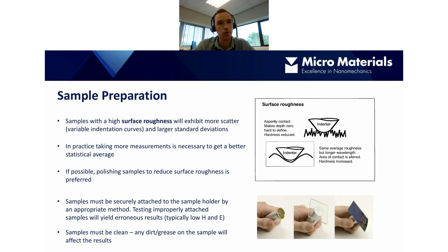It's also worth mentioning that the samples should be securely attached to the sample holder. You can see a few examples of some samples here. If the sample is not properly attached, then this will give us erroneous results, typically low hardness and modulus values, because when you're performing an indentation, you're actually pushing the whole sample back if it's not been adhered to the sample holder properly. And of course, the samples must be clean. Any dirt or grease on the sample, for example if you touch it with your finger, will likely affect the indentation curve and therefore the analysis results.